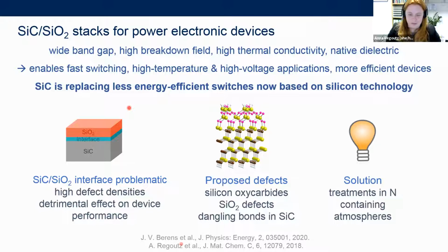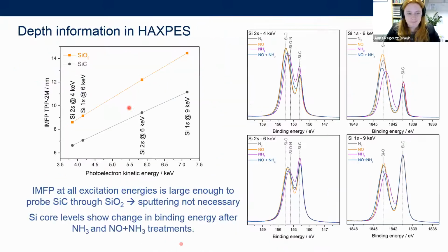So this is again where the photoemission comes in. I don't need to remind you, right, that HAXPES is great because we can look deeper, so we can look at the buried interface, but we can also tune our probing depth by choosing very carefully the excitation energy and also which line we look at. If you remember the photoelectric effect equation, these are all things that are quite important. We can then tune our probing depth. So for a specific device, we can change the probing depth of the X-ray photoelectron spectroscopy setup.